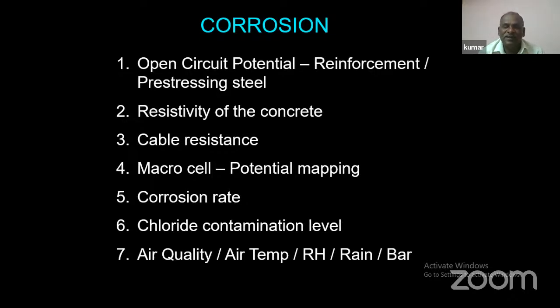The second one, resistivity of the concrete. When the concrete undergoes deterioration, the deterioration means there is carbonation. How does the carbonation happen? It is CO2 or industrial pollution facing the concrete. The concrete has a reaction, for example, CO2 reacting with Ca(OH)2 forms calcium carbonate. So that is the way the Ca(OH)2 is consumed as calcium carbonate.